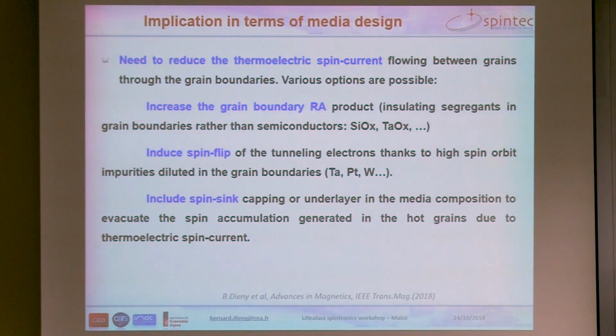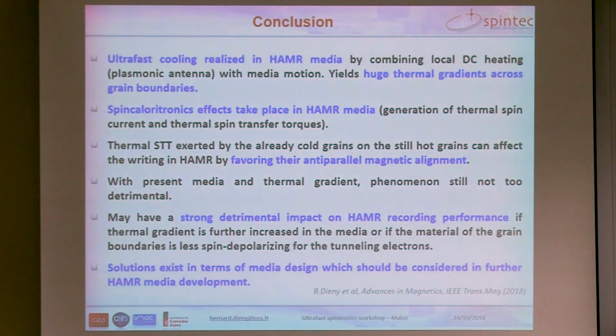So these are various things which can be tried, but the general idea is that nowadays we are still okay because the thermal gradients are not too high. I mean, of the order of 8 to 10 Kelvin per nanometer. But if we go as expected in the roadmap to 14 or 18 Kelvin per nanometer, we will reach this region where the impact of this phenomenon is really very serious in terms of signal-to-noise ratio.